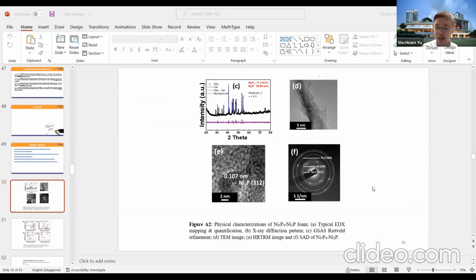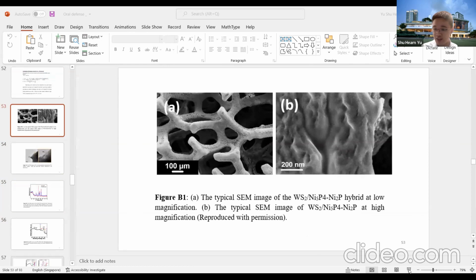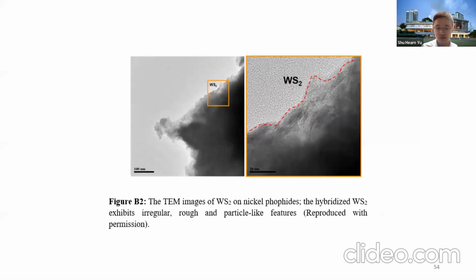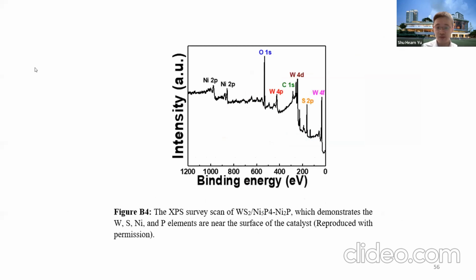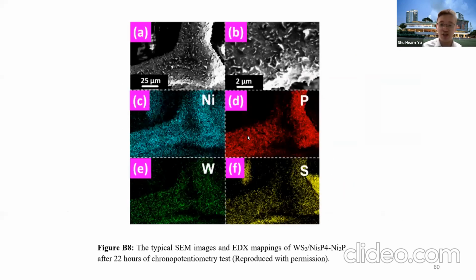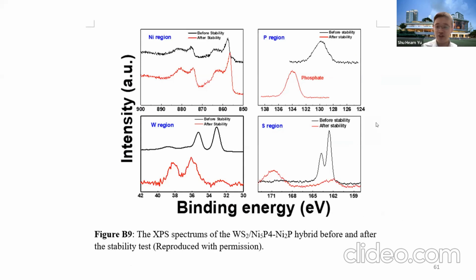I think I have one slide. Let me see whether I have a slide here. Yeah, these are the structures. So after the 22 hours of testing, it becomes a bit ugly. Yeah, and then you can see that the phosphate will form here. Phosphate formation is an oxidation reaction. Although at the cathode we have the hydrogen evolution reaction, which should be at a negative potential, in the corrosive environment everything can happen.